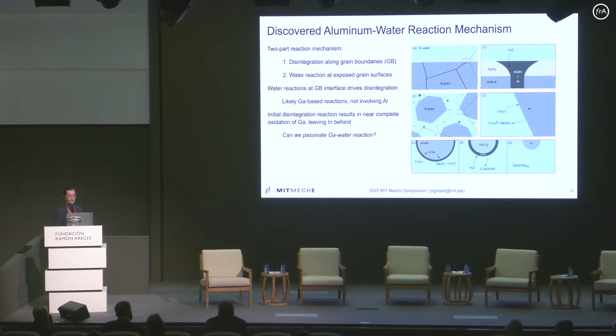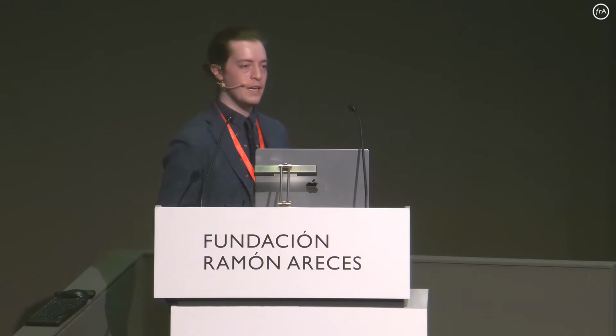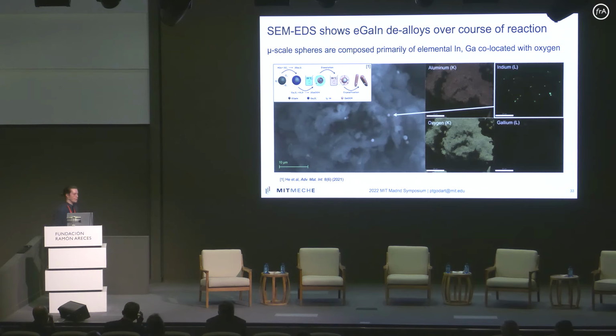And what we're seeing as well is that this confirmed the fact that in normal conditions, the gallium was also being oxidized, which explained why we were not able to recover it. The gallium turns to gallium hydroxide or gallium oxyhydroxide, and we're left with solid indium spheres, as you can see from this energy dispersive spectroscopy image here. Both of which are very difficult to separate out from that aluminum, and would require a significant amount of energy.